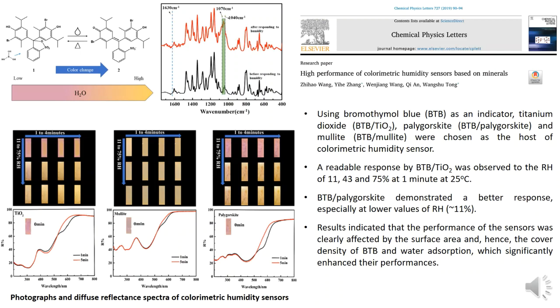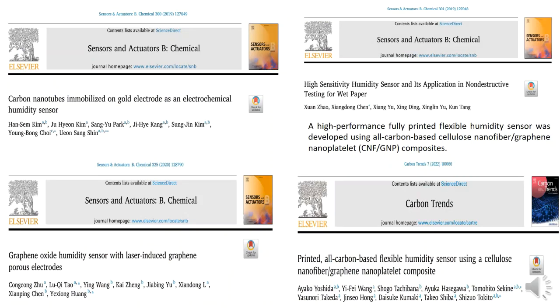Results indicated that the performance of the sensor was clearly affected by the surface area, and so the coverage density of BTB and water adsorption would significantly enhance their performance. And you can see here the change in the color of bromothymol blue in response to change in the value of relative humidity. These are other examples of humidity sensors based on gold electrodes, based on laser-induced graphene porous electrodes, and all carbon-based flexible humidity sensors using cellulose nanofibers.